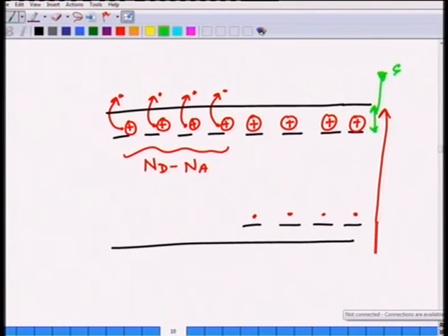But also please notice that this is a very powerful experiment. Why I have taught you this is that it is a good characterization technique. What do you notice? Suppose you measured carrier concentration in a full temperature range, from very low to reasonably high temperature. What different information can you get out of it? Notice this slope is essentially ED prime, and this quantity is EG.